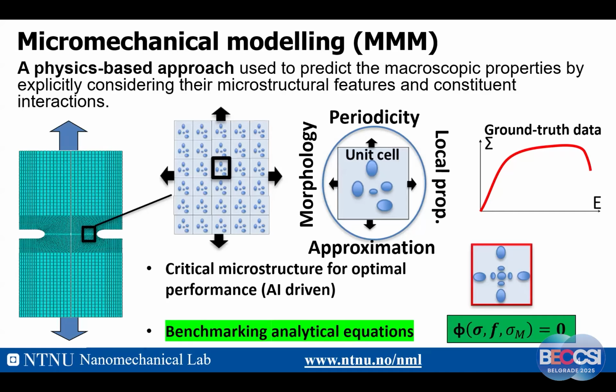And then with the unit cell, we can study the morphology. That includes the size, shape, and distribution of these phases, and the morphology and local properties on the left, and the macroscopic behavior on the right. So on the right-hand side we have ground truth data. That is data we can use for benchmarking analytic results, for example, benchmarking the Gurson model and the GTN model. We can use AI to identify the critical microstructure which can realize the optimal performance. So this is going to be the optimal microstructure, and these things we can do with micromechanical modeling.